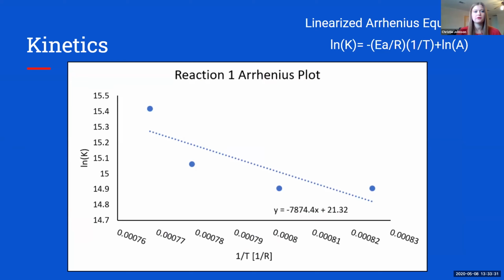And now I'm going to go into sort of how we validated our kinetics. So what you see here is an Arrhenius plot, and the way that we generated this was at each different temperature, we chose values for the frequency factor and activation energy that made the curves fit at that temperature. And these were all different frequency factor and activation energy. The challenge here was finding one set of kinetics that would work and track with temperature as it changed. So once we had modeled at each temperature some kinetics that would fit, we plotted all of these on this Arrhenius plot and were able to regress out one set of kinetics that would track with temperature.